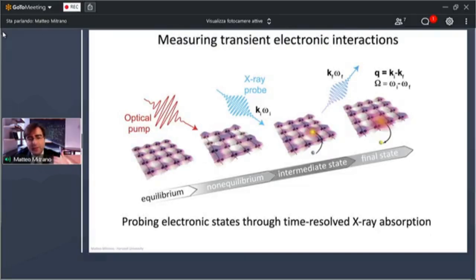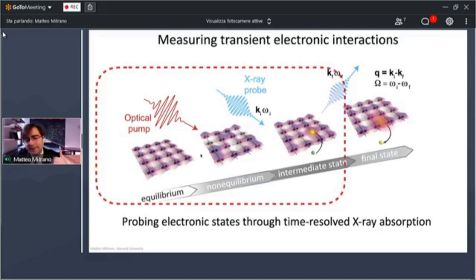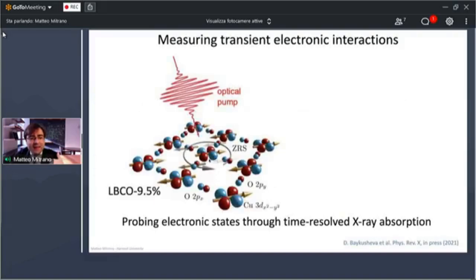So again, we looked at the scattering process. We now make use only of the first part of the scattering process, that is essentially an X-ray absorption, and we probe with this the electronic density of states of this material. And the density of states of this high-temperature superconductor at the Fermi level are essentially determined by copper and oxygen orbitals in plane that also hybridize in a state that is usually called Zhang-Rice singlet.